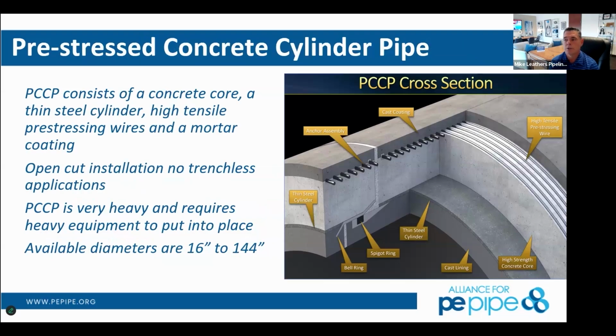So it was created to provide tensile strength to concrete. So the pre-stressing wires, as you can see, helped enable that and give tensile strength to that concrete by also creating a thinner wall concrete, which could reduce some of your costs and things of that nature. This steel cylinder was then added inside that concrete, or on the interior of that concrete if it's lined instead of encased. And that gives you that watertight membrane with the concrete, and then the wires being put around it also reduce that cost with a thinner gauge steel.